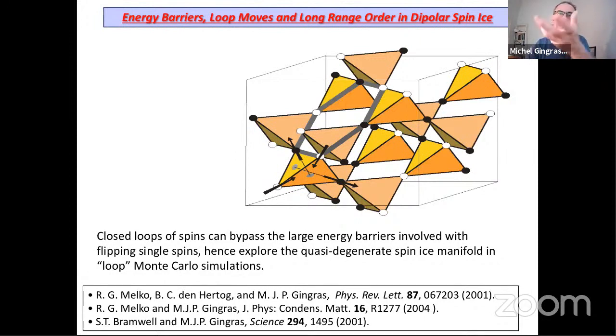And instead of trying to do single spin flip in the Monte Carlo and go over these large energy barriers, we tried to do what I illustrated earlier with the Kagome system: generate closed loops, which takes us from one ground state to the other, which, if the interactions were nearest neighbor, these excitations, these loops, would cost strictly zero energy. But now the interactions are not nearest neighbor. They have these long range dipole-dipole interactions.